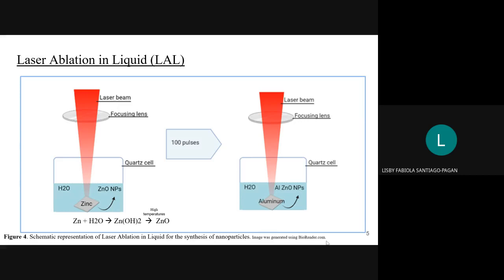In addition to the synthesis of these nanoparticles using laser ablation, the researchers also wanted to dope the nanoparticles with a material that could potentially enhance the activity. So aluminum was chosen for its availability and low toxicity. The doping of the nanoparticles was also achieved using the same technique, by replacing the zinc target with an aluminum surface after 100 pulses of ablation. The synthesis of nanoparticles here via laser ablation in liquid is presented as a simple, fast, efficient, and environmentally greener alternative for the synthesis of nanoparticles.